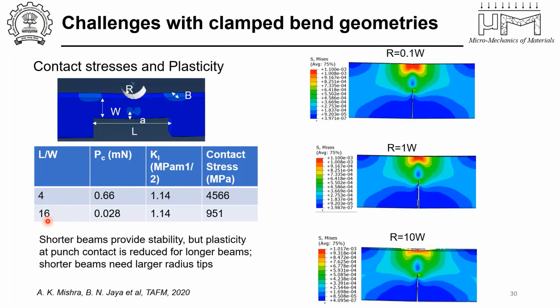For a given fracture toughness of the material, if I keep the K1C fixed, then the critical load at which the material would break would be higher for a lower L/W, or lower aspect ratio, beam, but that also corresponds to a higher contact stress at the point of the punch making contact with your beam. So one should not allow yielding to take place because of contact. That is the problem that we need to overcome, and it can be overcome by using a larger radius of the punch or the indenter.